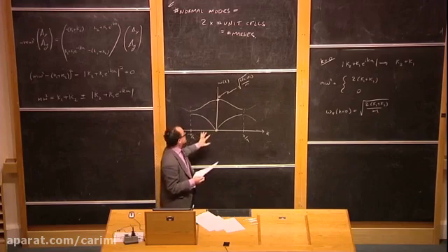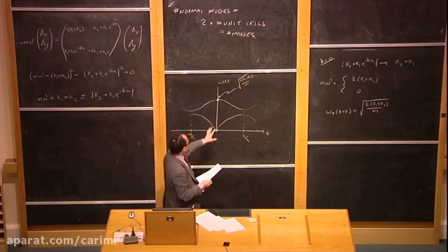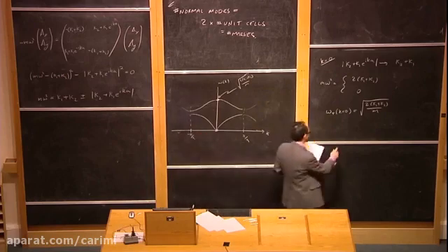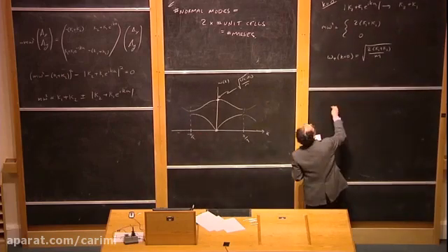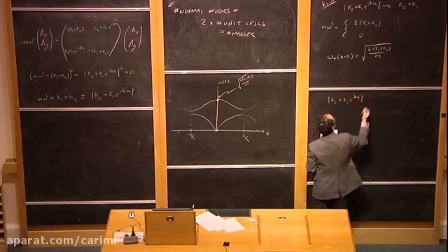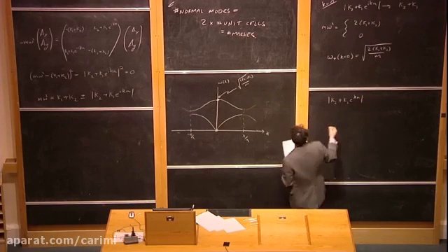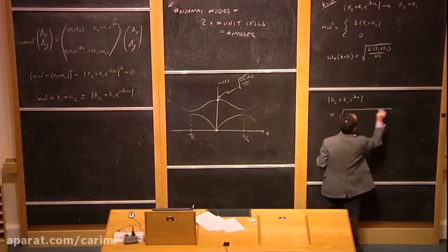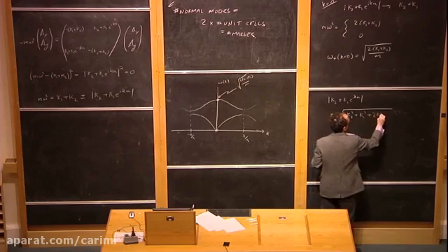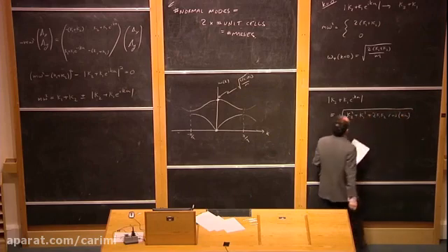Now, to convince ourselves that that's what's going on with this equation, we have to actually do a little bit more math and expand the dispersion curve near k equals 0. So let's see how we do that. Let's take kappa 2 plus kappa 1 e to the i k a. That quantity there can be written as the square root of kappa 2 squared plus kappa 1 squared plus 2 kappa 1 kappa 2 cosine of k a. Just by multiplying that out.